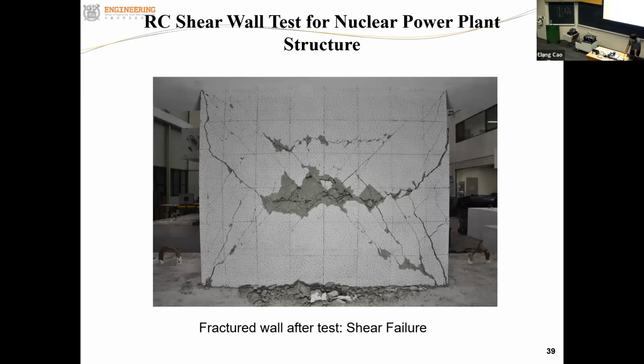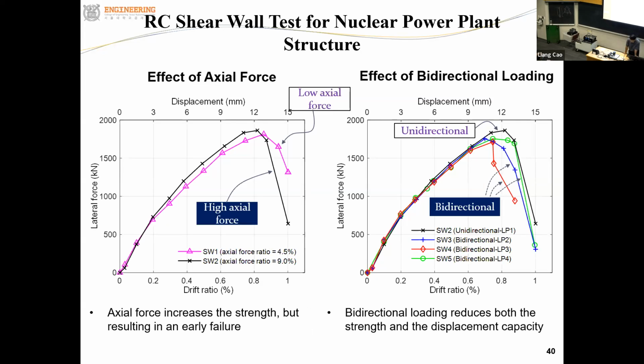All right, that shows the damage pattern after that test. The typical shear failure, and the wall was designed to have the shear failure. So we have this kind of damage after the test. And this shows the summary of the test result. As I said, we conducted the unidirectional and the bidirectional test, and we are interested in seeing the effect of the axial force and also the effect of the bidirectional loading compared to the unidirectional loading only. The left-hand side figure shows the effect of the axial force.